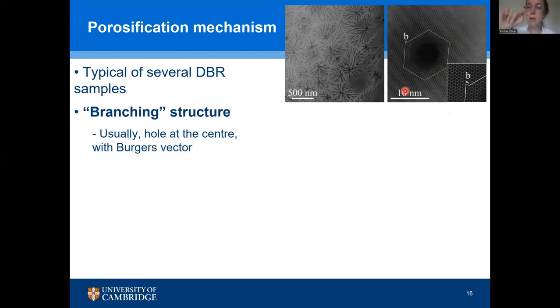And if we did that in a perfect crystal, we'd be able to go round and it would close. And if we take that closed circuit and take the same number of steps around a defect, around a dislocation, the circuit doesn't close. So this hexagonal ring you're seeing is my Burgers circuit. It would close with the number of steps we've taken if we were in the perfect crystal, but actually it doesn't quite close. And we have this lack of closure vector, this displacement where it ought to be closed and isn't, and that's expressive of the fact that there's a defect that was running down through this hole.